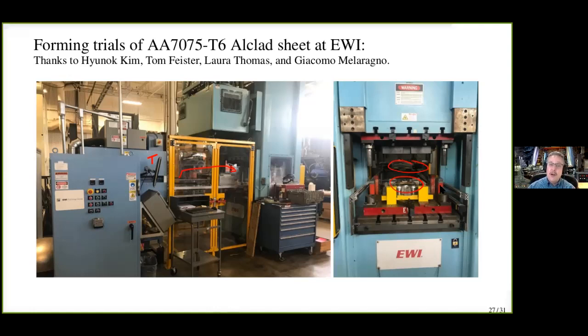So we got the part into the dies at the right time, at the right temperature. We stamped it. Stamping was fast enough so we didn't cool down too much during the stamping process, and we extracted it, and we were within our forming process temperature time window.